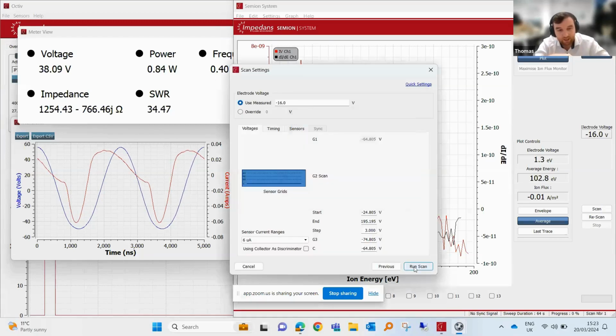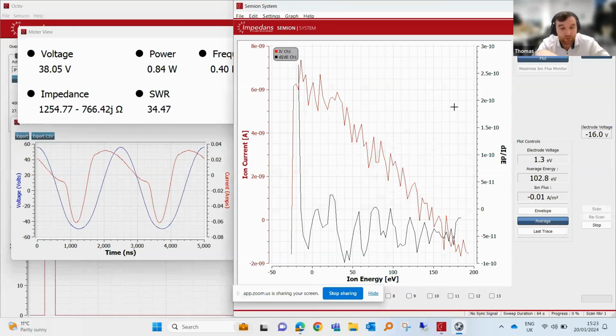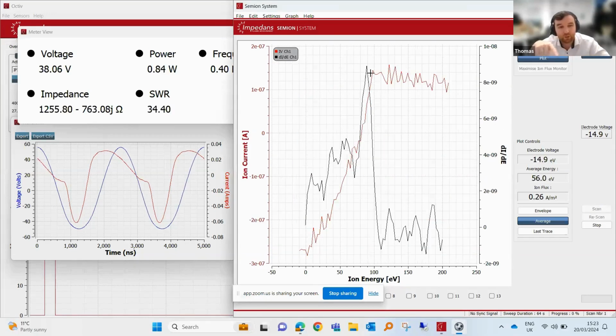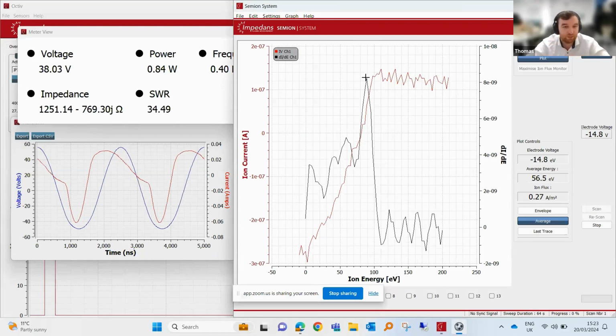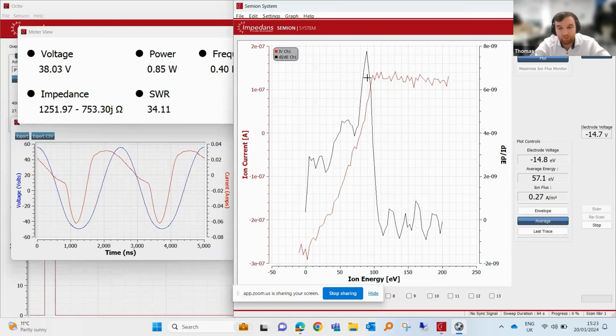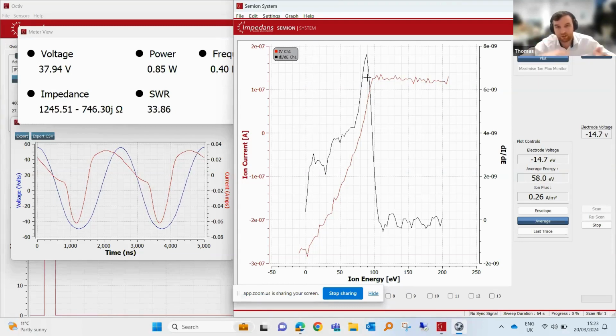Right now you can see there's a sinusoidal voltage being applied, and then you see a distorted current. That's normal; there are collisions in the plasma and so on. Now on the right-hand side, you can see the Semion software, which is actively collecting the ion energy distribution function data. You can see the average electrode voltage, which is about minus 15 volts, and then the typical bimodal 400 kilohertz distribution.